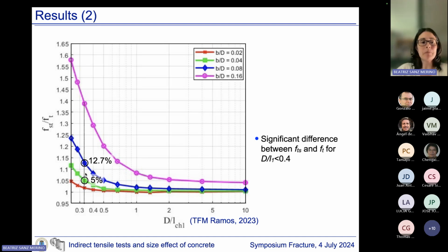So it seems that maybe for the new mixtures, the conditions of the Brazilian test should be reviewed, because maybe this bandwidth is not admissible. But if they have to be used for any reason, because otherwise the test is very difficult to perform, then this error should be taken into account, and the tensile strength obtained should be corrected by using the iterative methods that I mentioned. For this, analytical expressions of this curve will be provided in the future. We didn't include them in this presentation, but we are working on that.